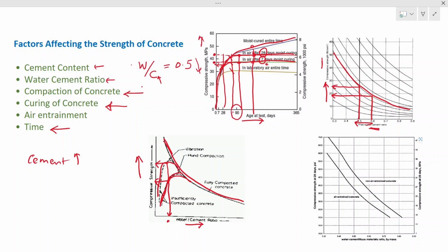In addition to this, I want to mention the additives of the concrete. When you consider normal concrete, the strength development will not be the same as concrete with additives. Sometimes when you add additives like fly ash, the strength gain rate will be reduced. In such cases, we will get the strength, but not at 28 days, but at a later date. For such situations, when you do the mix design, we specify to check the strength of the concrete at 28 days and 56 days.